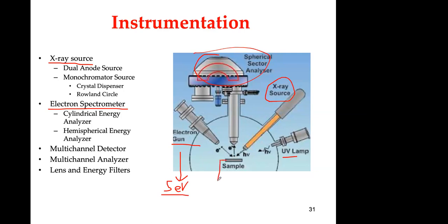Remember that you want to connect the sample to ground so that electrons can come from ground to compensate for the charge that is being formed here, because you're getting electrons out. So you have electrons from ground coming into the sample. But if that's not enough, then you can have an electron gun with low energy to just make a splash of low energy electrons to the surface to compensate for the charge. And that helps. So some instruments have that as well.